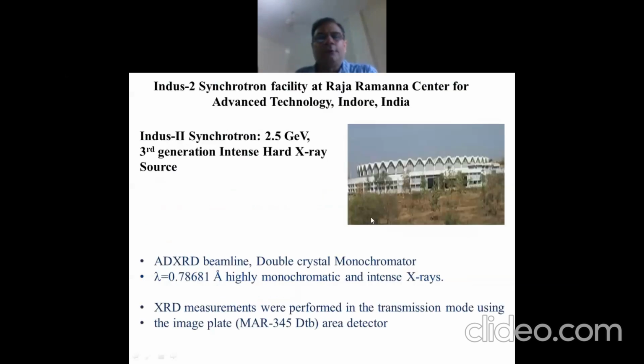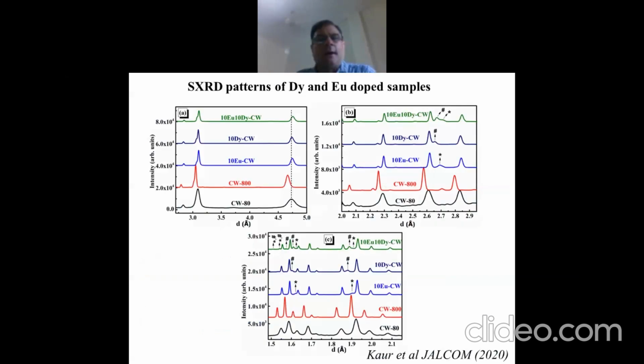Indus 2, as you know, is a third generation hard X-ray source. The maximum energy of the beam is 2.5 giga electron volts. You can see a picture of the circular building which houses the storage ring and the synchrotron. We used the angle dispersive X-ray diffraction beam line, which has a double crystal monochromator. The wavelength used was 0.78681 angstrom, highly monochromatic and intense X-rays, so you get very sharp X-ray peaks. The diffraction pattern was recorded in transmission geometry using an image plate detector.